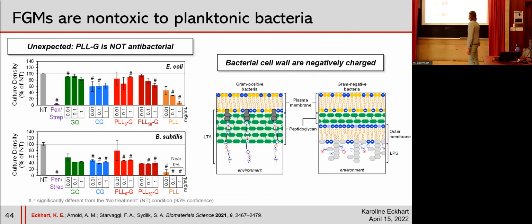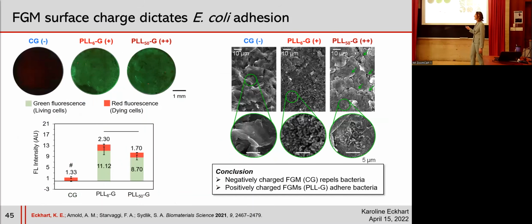Because bacterial cell walls have these polymer chains sticking out through the cell wall that are anionic, we expected that the different charge of the FGM would be able to control bacterial adhesion through electrostatic interactions. And we tested this by culturing pellets of our negatively charged clay and graphene with our positively charged PLLGs, and then staining the bacteria with a dual dye stain where living cells are stained green and dying cells are red. And we can see that the clay and graphene has very few bacterial cells on it. It doesn't have very much green or red at all. So this one is considered bacterial repulsive because the negatively charged material is repelling the negatively charged bacteria.